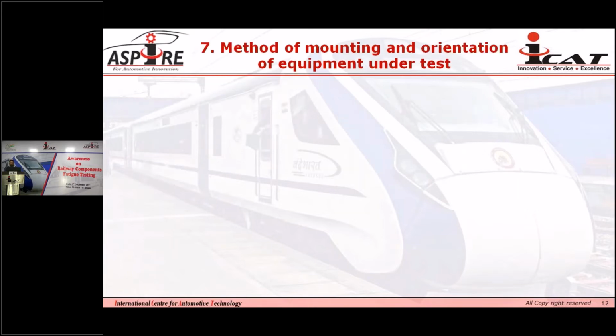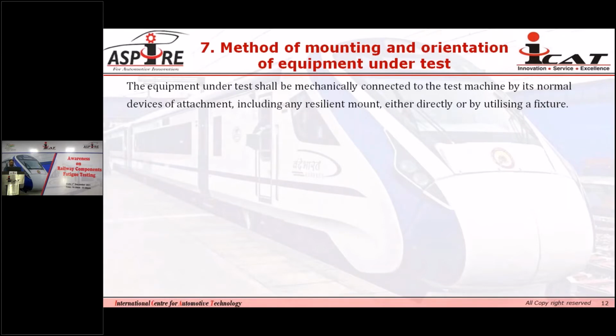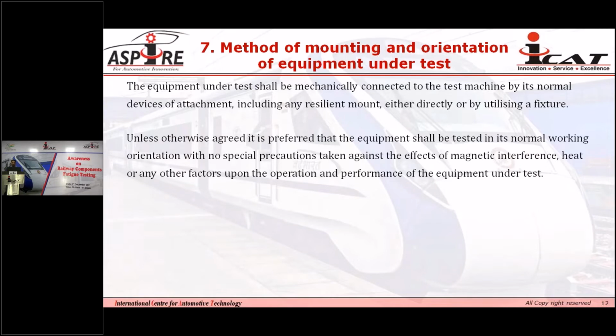Now, what is the method of mounting and orientation of equipment under the test? The equipment under the test shall be mechanically connected to the test machine by its normal devices of attachment, including any resilient mount, either directly or by utilizing a fixture. Unless otherwise agreed, it is preferred that the equipment shall be tested in its normal working orientation with no special precautions taken against the effects of magnetic interference, heat, or any other factors upon the operation and performance of the equipment under test.